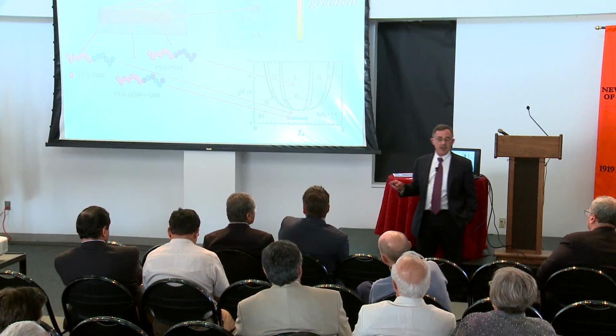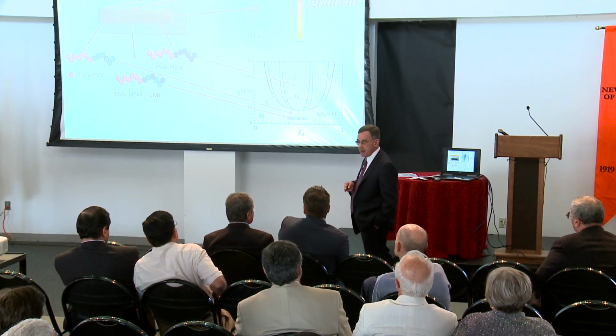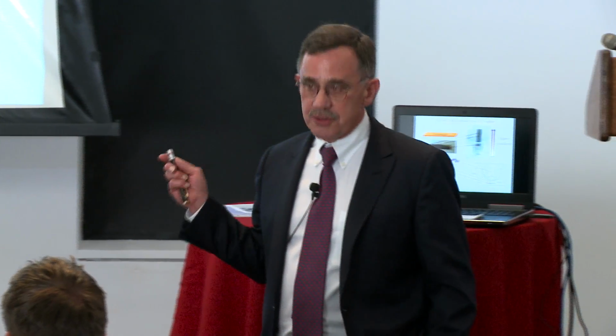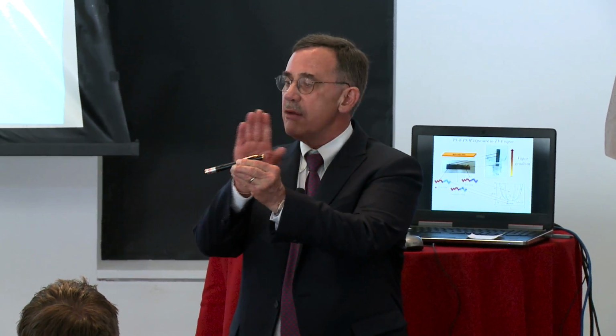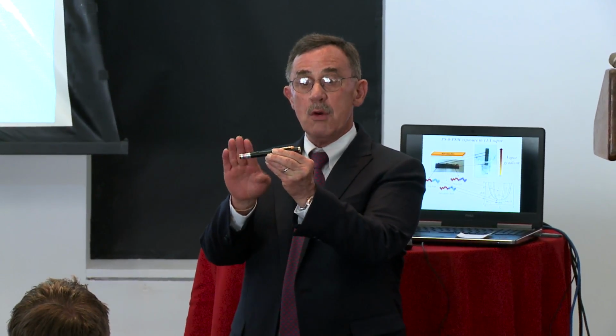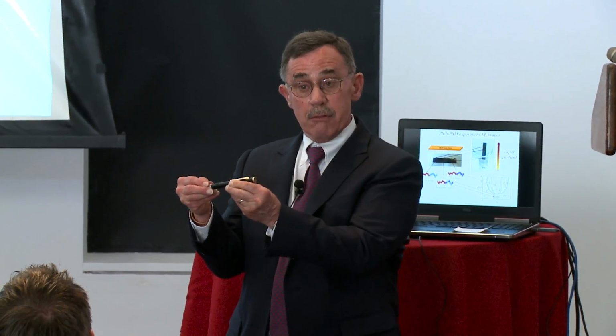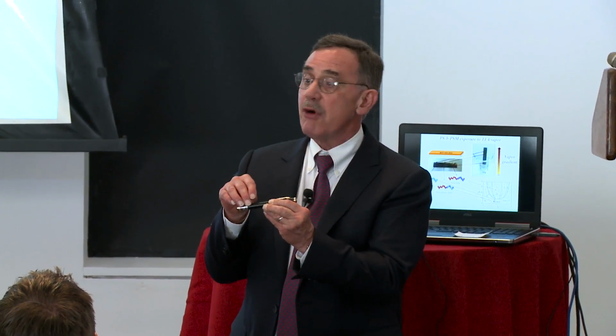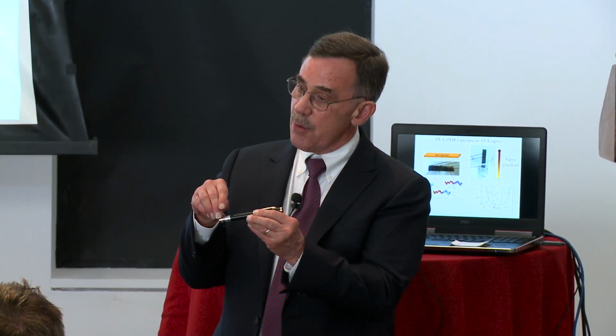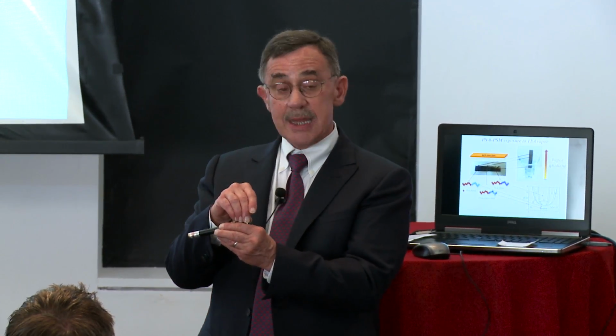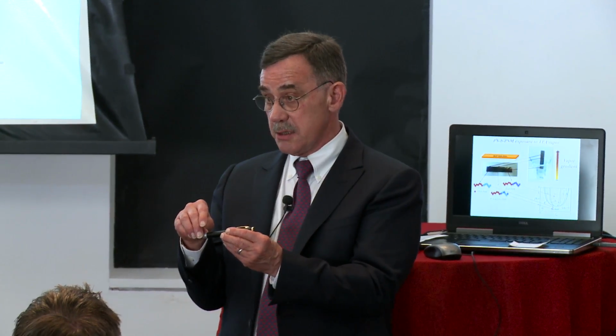Now, for those of you who have worked in industry or who have worked with silicon or have worked with metals, this is exactly what's called zone refinement, whereby I can take a front, I can have a film that's ordered over here and disordered, and if I move the ordering front across the film, these structures here I can order and get very good lateral ordering, and further ordering on the film is going to grow epitaxially on what I have already. And so I can take a film and I can just have this ordering front propagate across the surface, and I can do it very slowly. And what that allows me to do is to use this epitaxial growth to generate perfection laterally in the film.